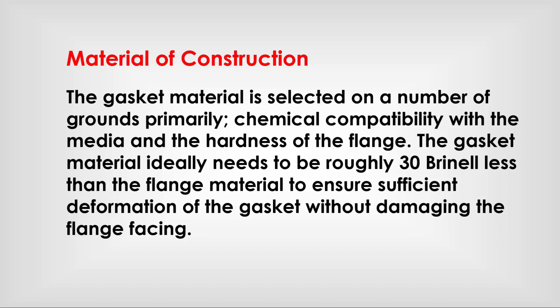Material of construction: the gasket material is selected primarily on chemical compatibility with the media and the hardness of the flange. The gasket material ideally needs to be roughly 30 Brinell less than the flange material hardness to ensure sufficient deformation of the gasket without damaging the flange facing.